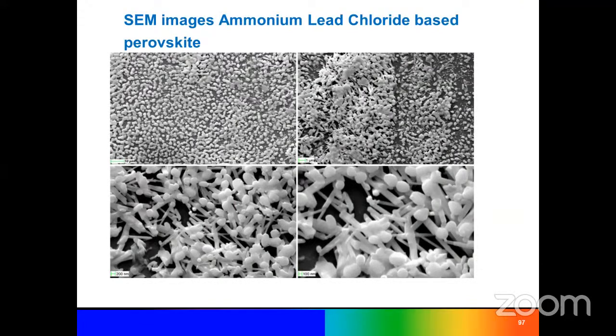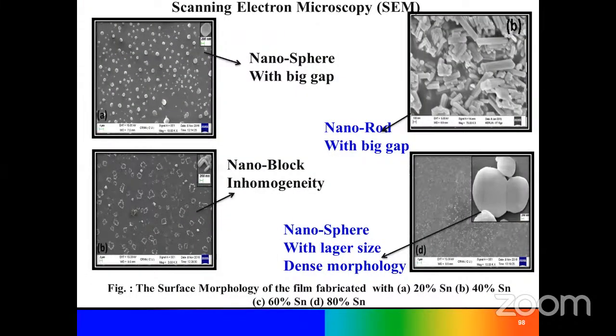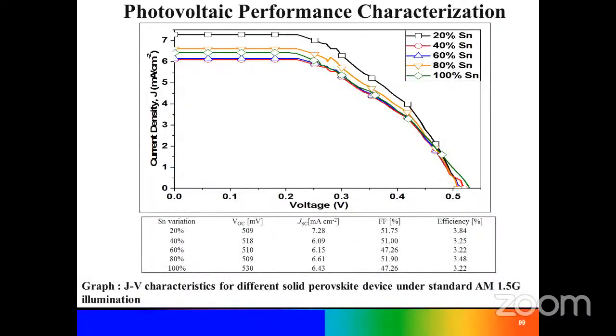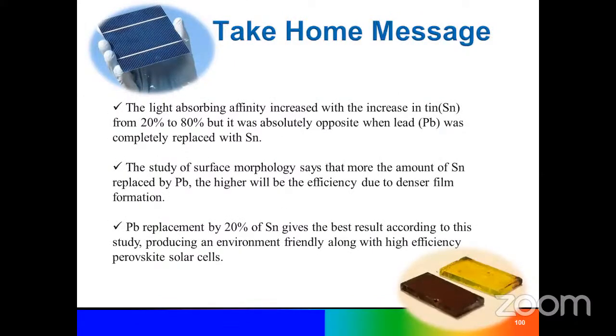Then finally, we check the morphology and XRD characterizations for confirmation of the purity of phase formation and the behavior of the cell. And then we observed different types of tuning percentage. When we tune, we get different types of morphology, like nanorod, nanosphere, all those things. So we optimize this morphology after checking the electrical property of the cells. Then here we got around 3.84 at 20% Sn doping, which is the maximum. So here we can conclude that 20% Sn doping is giving the maximum efficiency, and we can replace the lead by around 20%; beyond that the efficiency is decreasing.